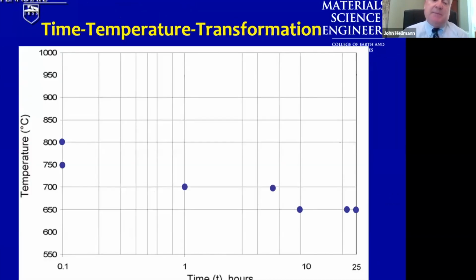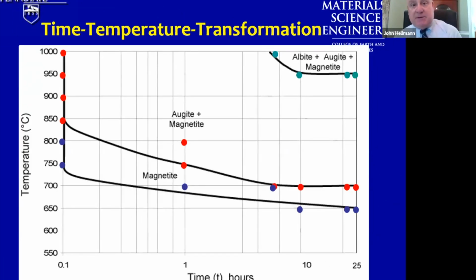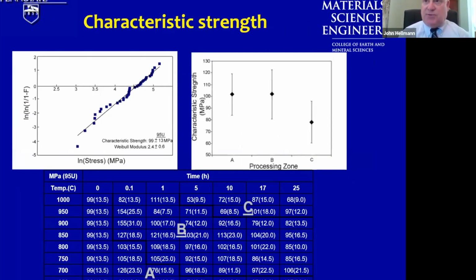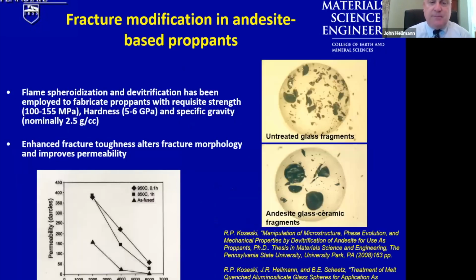We examined the time temperature transformation behavior of, in this case, an andesite-based material, found out where the different crystalline phase fields were accentuated in time temperature behavior, manufactured materials in those regions, and examined their characteristic strength using the Weibull approach I mentioned previously. Characteristic strengths were quite impressive, on the order of intermediate strength proppants, commercially available in the industry, state-of-the-art stuff, and that the